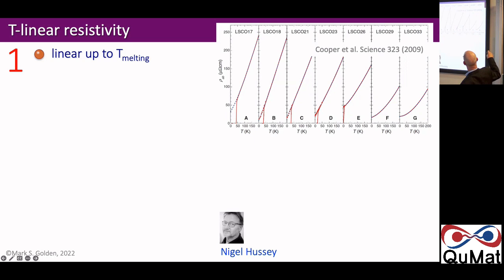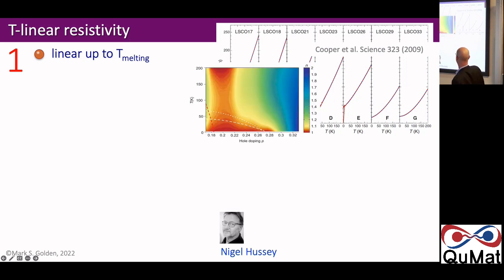And you see doping levels like this 18%, which looks exactly like the PowerPoint cartoon of the resistivity curve I told you. You have zero resistivity at low temperature, a jump to a finite value, and then linear all the way. In this case, it was measured up to room temperature. But what Nigel noticed with his team is that all of these resistivity curves, maybe with an exception of the very last one, none of them are T-squared like. They all have a mixture of T-linear and higher powers of T. So there seems to be strangeness in all of these different compositions.